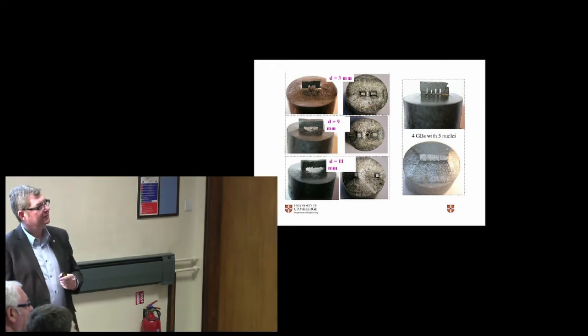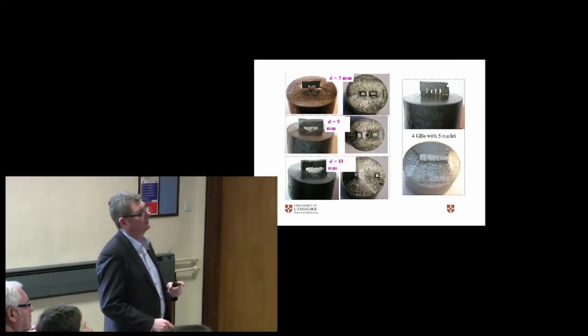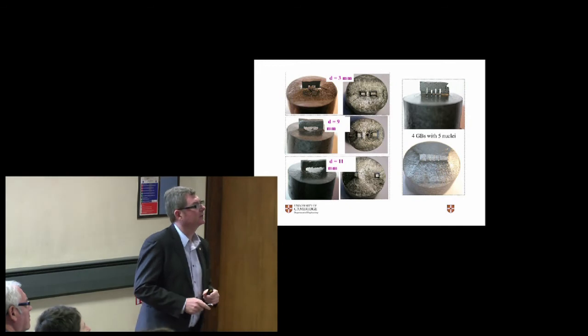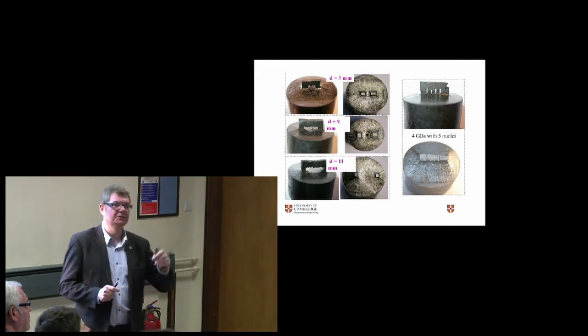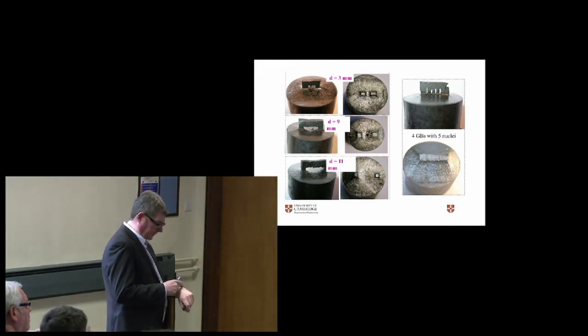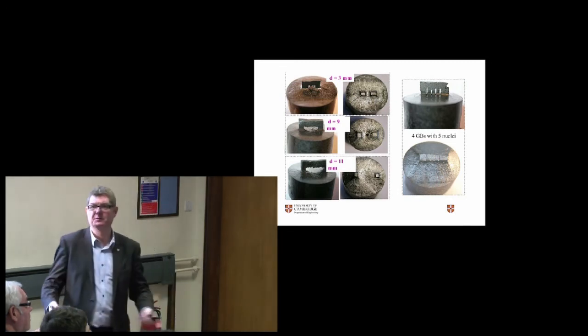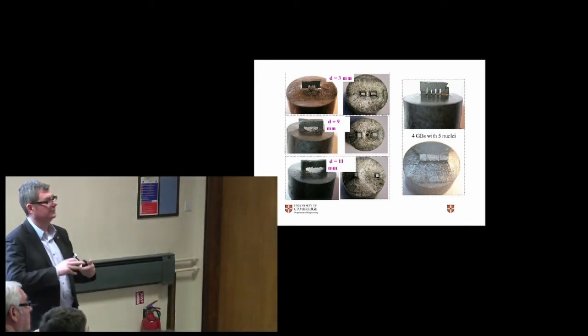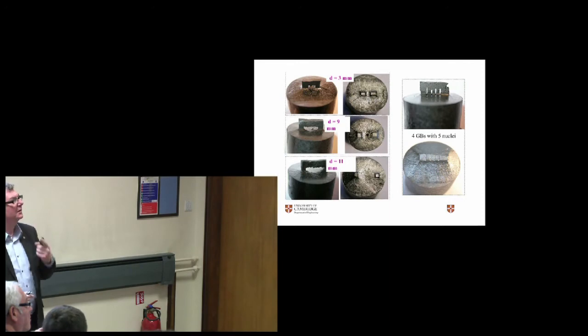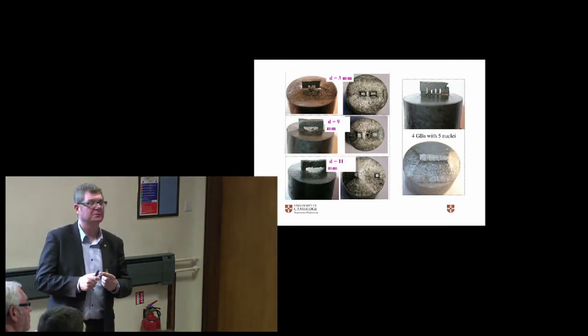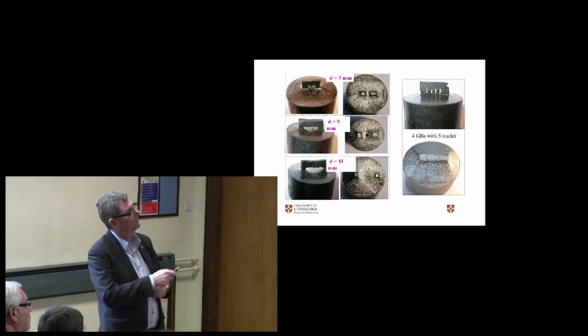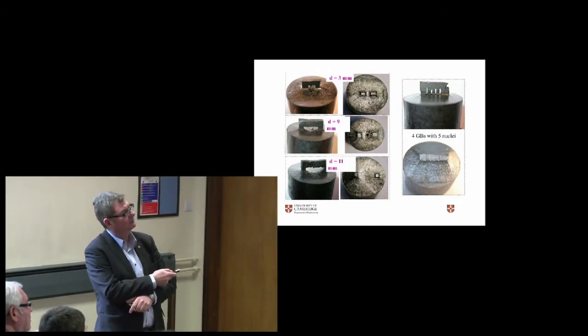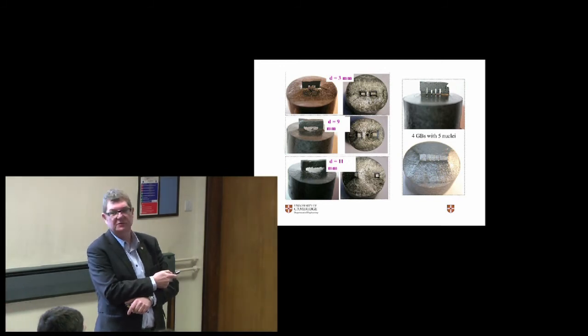Okay, so I mentioned multiseeding earlier. This was an experiment we did a couple of years ago. It's all right using a single seed, but you may want a sample of conformal geometry. You might want to put it in a motor, or you might want it for a shim of a magnet, and a cylinder may not be the most appropriate shape. So we took a piece of melt processed material, and we cut out the middle, which gives us two legs, and we used each leg as a seed.